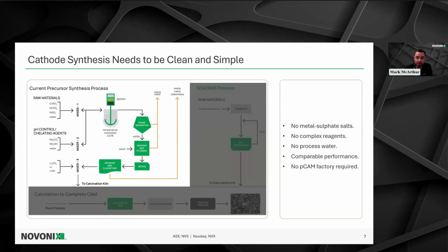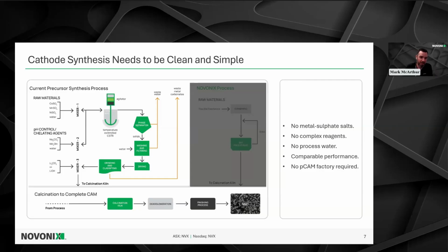You can then take that powder, combine it in a mixer with a lithium source, typically lithium carbonate or lithium hydroxide, and then you conduct the lithiation step, the step where you take the PCAM and turn it into a CAM, NMC material. So powder is loaded typically into a kiln. What's used conventionally is a roller hearth kiln. And then there are some further downstream processes to de-agglomerate the powder and get it into the shape that you want. And also you have the option of finishing it up. What I mean by that is adding any secret sauce dopants or surface coatings before you can have a fully fledged NMC powder ready to go into a cathode electrode to put into a battery cell.